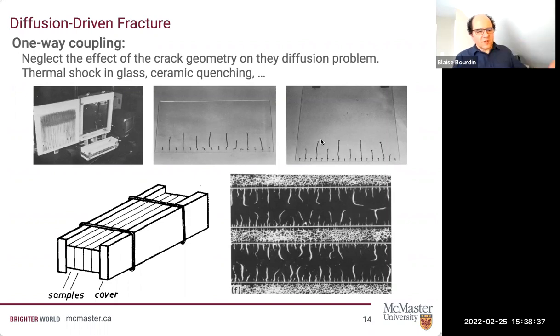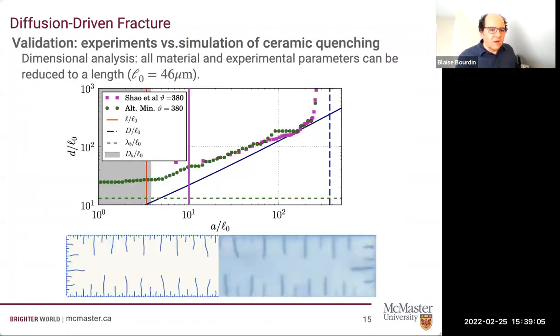And there's tons of work on that, or you can do that on a slightly thicker sample. So these are ceramic slabs that have been quenched. So this would be, let's say, the upper face, the face towards me, the lower face, the face towards you, and then against the upper face of a sample. So you unroll it, and you see these long transverse cracks, but also this crazing pattern on the side. So black is the material, white is the cracks. Again, in this case, the cracks are expected to grow orthogonal to the temperature level lines.